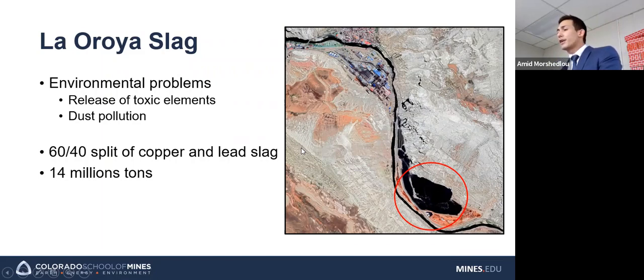So the slag created two environmental issues. One is that it would release toxic elements into the atmosphere through mechanisms like acid rain. And then also some of the slag particles were pretty fine, so you would get quite a bit of dust pollution into the area, and that causes a variety of issues.